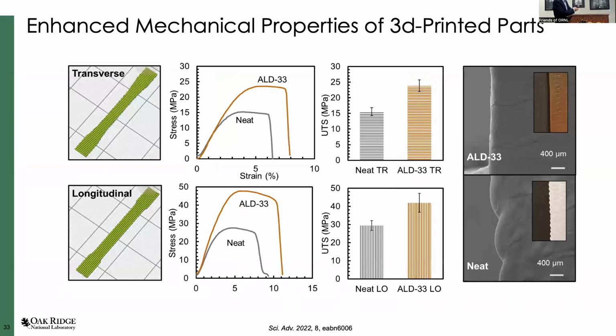Then we wanted to compare the directions. The transverse direction is this way, and the longitudinal direction is the other. Ideally there's no difference, but typically there is. Again, neat is the commercial ABS, and our ALD-33, because the cross-link is networked, is much, much stronger, about twice as good, and also has a much smoother interface. The interface is typically the weakness of 3D printing, when you go layer by layer, that's where the weakness comes from. But it's much smoother, so that's much better. That's what we are able to do.